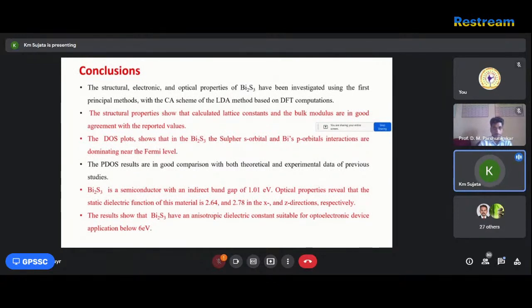Bismuth sulfide is a semiconductor with an indirect band gap of 1.01 electron volt. Optical property reveals that the static dielectric function of this material is 2.64 and 2.78 in the x and z directions respectively. The results show that bismuth sulfide has an anisotropic dielectric constant suitable for optoelectronic device applications below 6 electron volt.